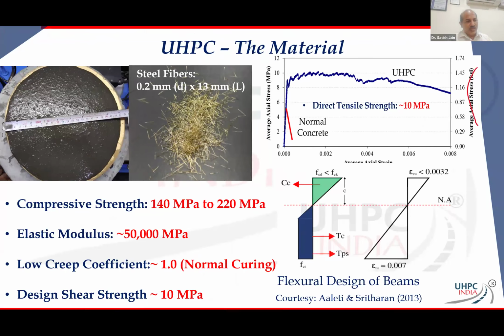So let's delve into the philosophy a little bit, right? Of course, I have a lot of slides to show on the application side of the thing, but I think for those who are still not aware, it's very important to understand the philosophy. We spoke about the fibers, right? Generally 13 mm fibers, but now a little bit of 20 mm fibers are also being used. So 0.2 extremely fine with a very, very high dosage, typically about 2% of volume of the UHPC. So when we say 2%, it's about 156 kilograms per cubic meter.